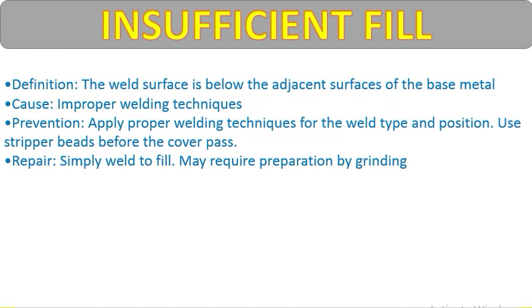Insufficient fill (underfill) — the weld surface is below the adjacent surface of the base metal. Cause: improper welding technique. Prevention: apply proper welding technique for the weld type and position; use stringer beads before the cover pass. If insufficient fill is present, use a stringer bead on that side, then apply the cover pass. Repair: simply fill — may require preparation by grinding.